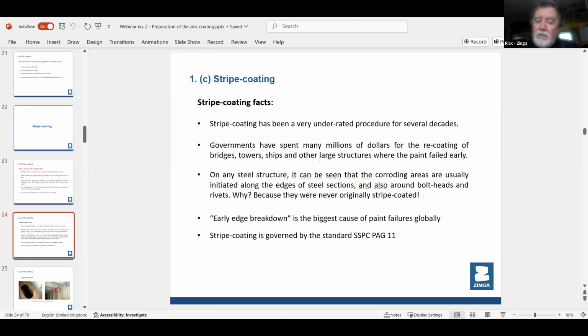but we still apply stripe coating to Zinga as well. So you're getting decent coverage over every single aspect of any project, whether it's a storage tank, a bridge, transmission towers. Every square millimeter must have the same thickness of zinc. And to do this, it takes stripe coating.